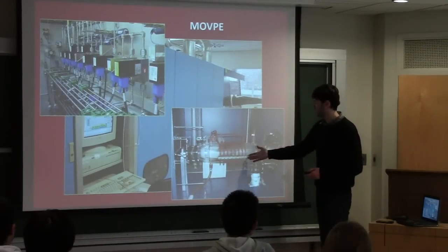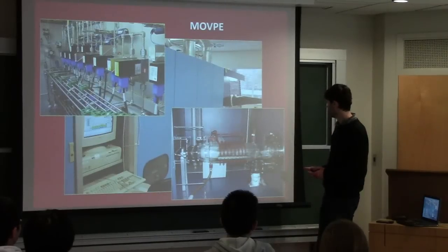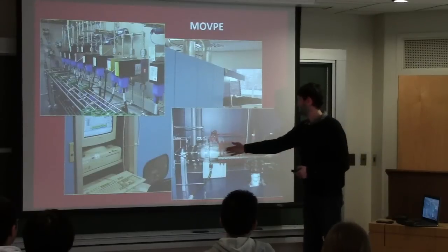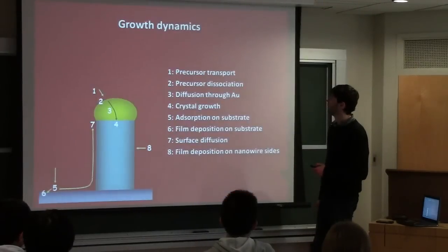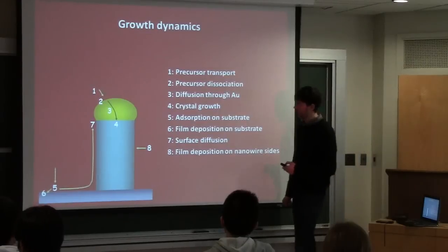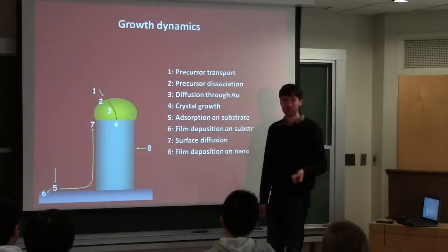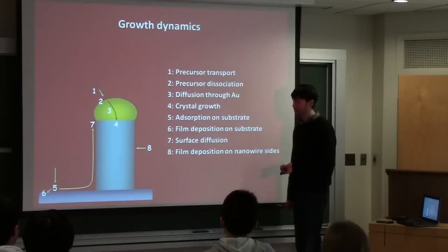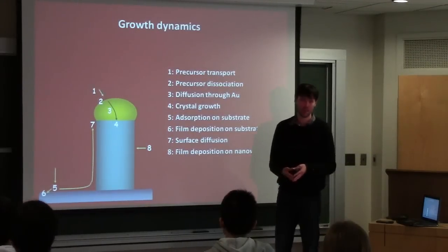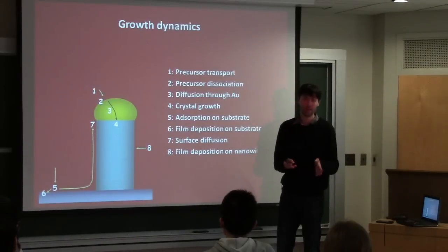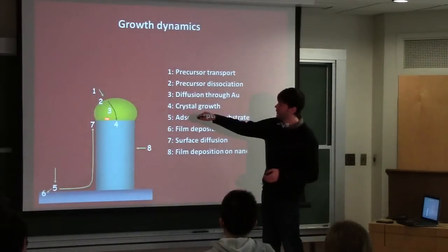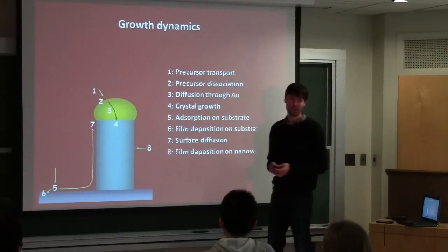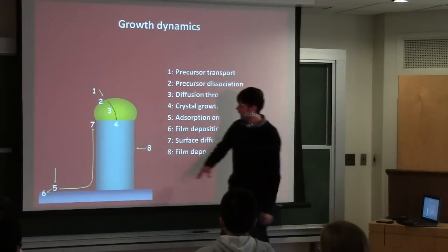Okay, and here you can see the photo of one of the reactors. There are all kinds of different models, but this is the tube where all these gases combine. And the nanowires that my group works with are produced using MOVPE, and it is also a very interesting and fascinating process how they grow, and quite a bit different from MBE. The biggest difference comes from the fact that you have this gold particle which catalyzes the growth. You can see in this diagram that this nanowire semiconductor only grows underneath the gold particle.